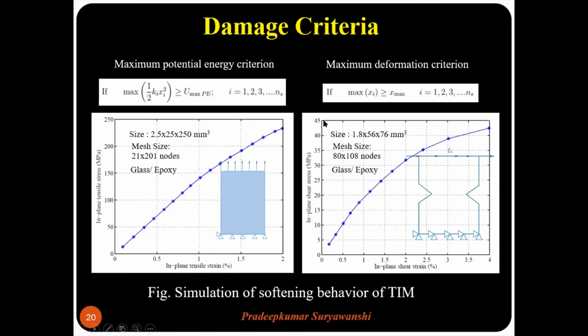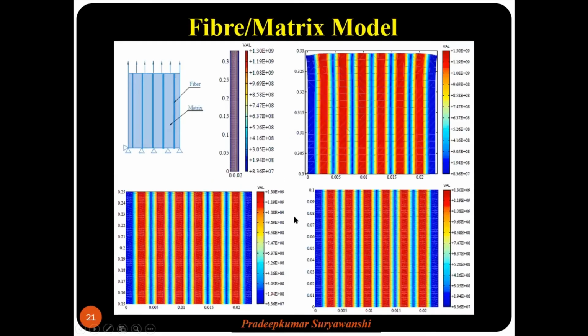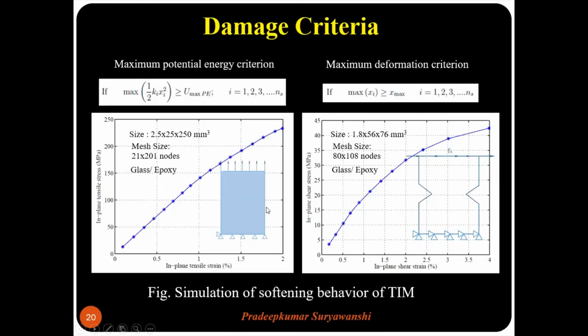Let us consider case C. Here again, the material is glass epoxy, is transversely isotropic, and we have simulated the in-plane tensile specimen and in-plane shear specimen. Okay, and these two tests for composite material result in something called as softening effect. That means the stress strain curve follows a decreasing slope. It is linear till some extent, and then it slowly drops. The slope is dropping here. Okay, that is because of this. In this area, there is a damage, and we have removed the springs depending upon the potential energy criteria. Similarly, in this case also, it's linear till somewhere here, and then the slope is dropping. So from this we can say our model is capable of simulating the softening behavior of the transversely isotropic materials.